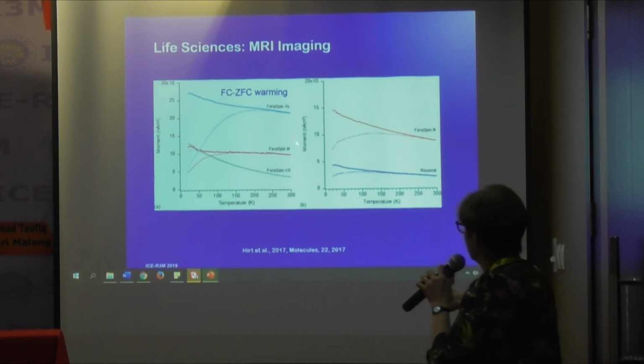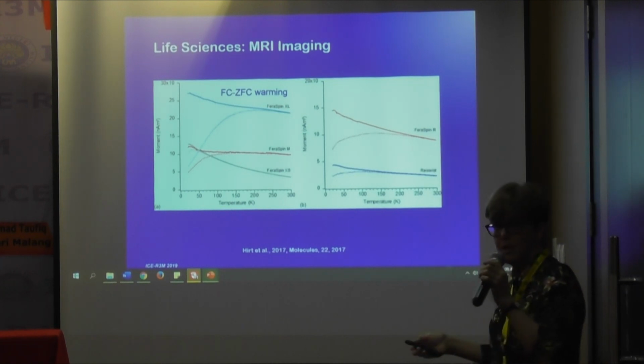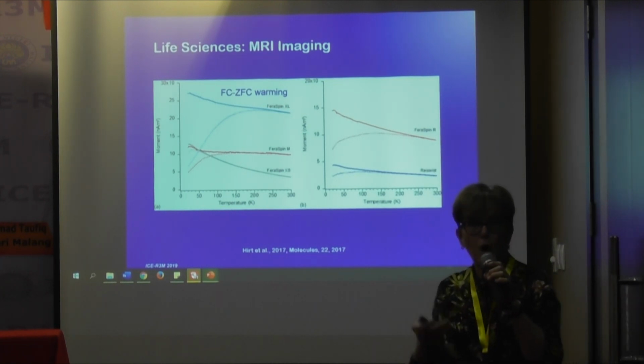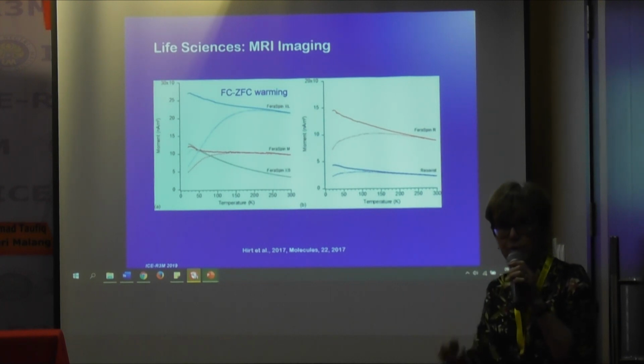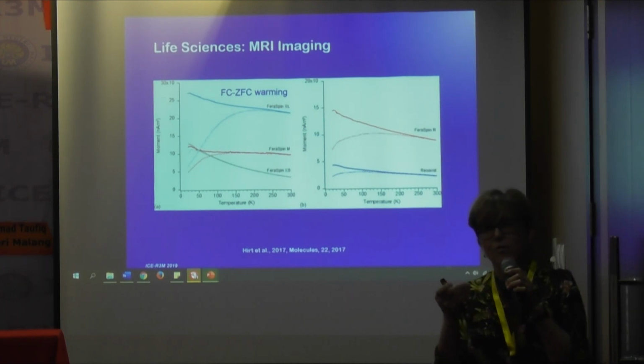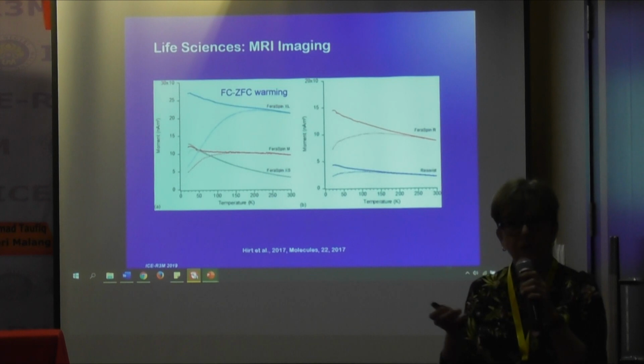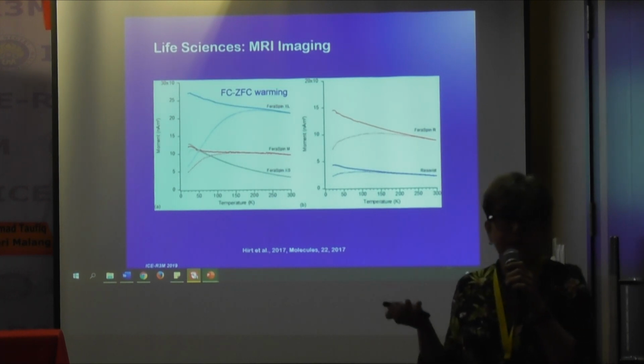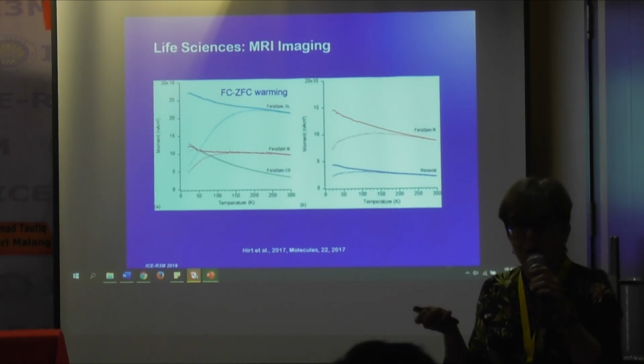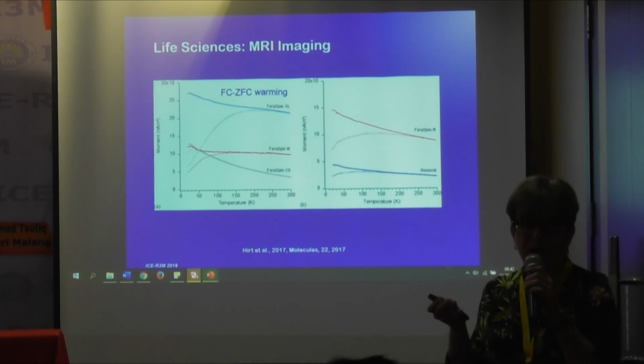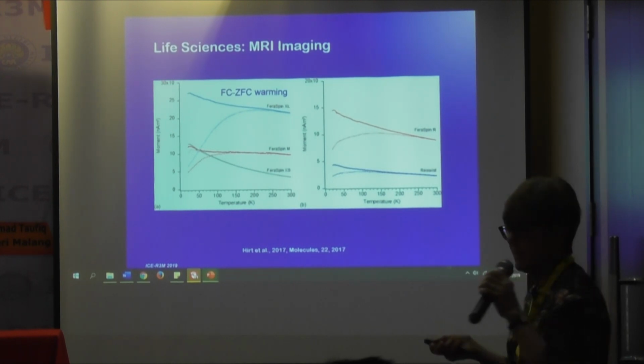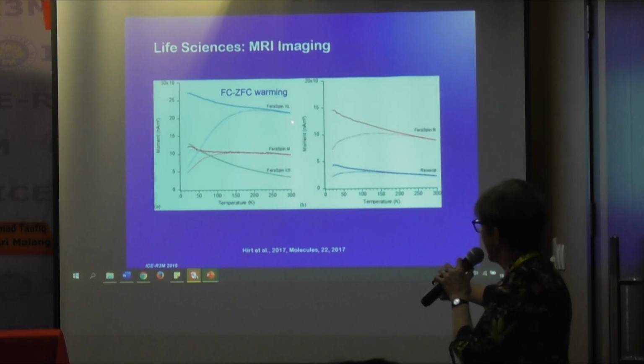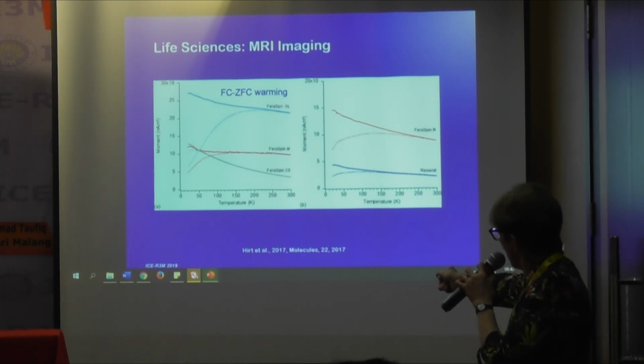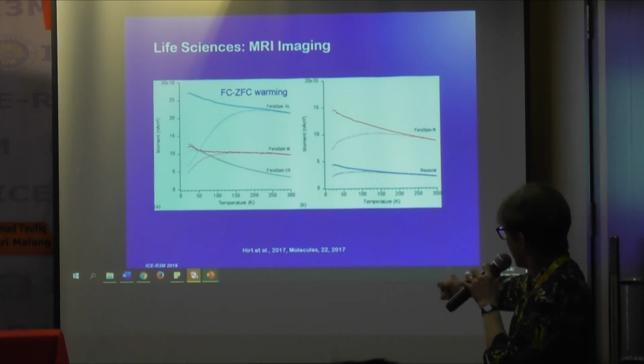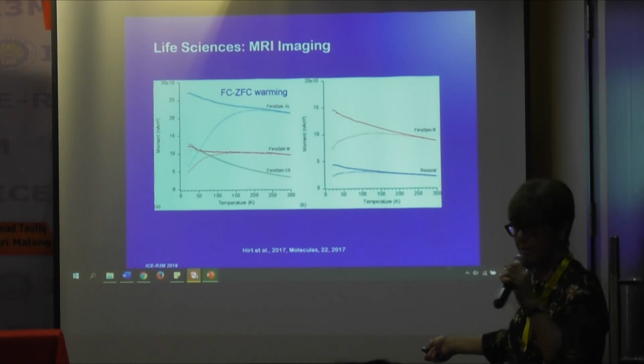Now what's interesting is where these two curves split. This is telling you about when the samples start to undergo blocking. So remember, for magnetite, on a scale of, let's say, 1 second, your blocking volume is going to be about 25 nanometers. So if we're close to 25 nanometers here, you can see this is blocking almost at room temperature. Those curves start to diverge very close to room temperature.